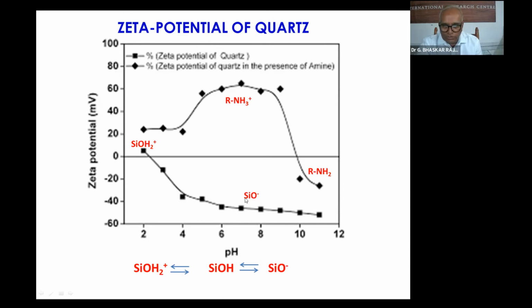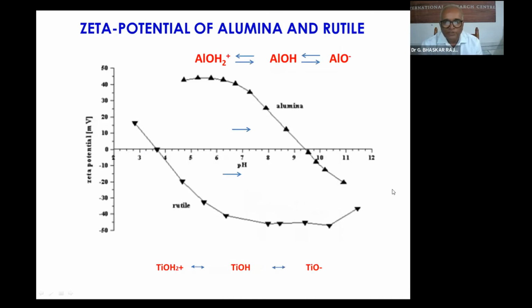So you choose in such a way that only silica is negatively charged and the other things will be positively charged. You select that particular pH so that you can achieve the selective adsorption of this amine onto the silica surface. Why do you float with this amine? This is a long chain hydrophobic molecule, so you have the hydrophobic nature once it gets adsorbed on this, and it gets separated by attaching to the air bubbles.